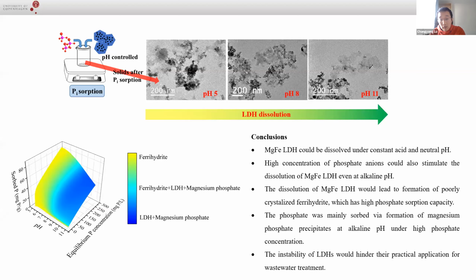And for the adsorption mechanism, we found that phosphate is mainly removed via the formation of magnesium phosphate precipitates at alkaline pH and high phosphate concentration. So we think that this material is actually not really stable for long-term use, and if we want to use it for practical application, we have to focus on increasing the stability.